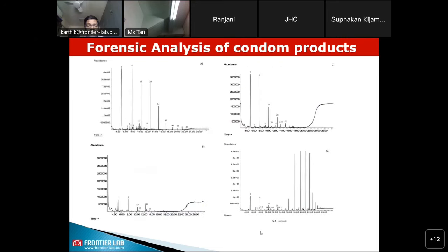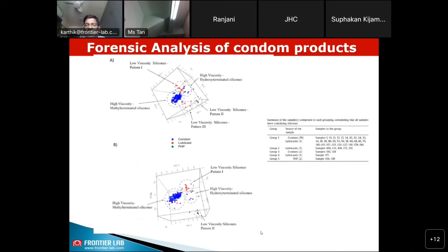Here is again the pyrogram of different condom samples and also the lubricants. In some cases they found that differentiation based on lubricant is much easier than on the condom sample, because the condom mostly has the same type of polymeric material, but the lubricants employed within the condom really allow them to do the differentiation. Here again, the clustering of this data set with multivariate statistical analysis allows you to see the different types of materials.